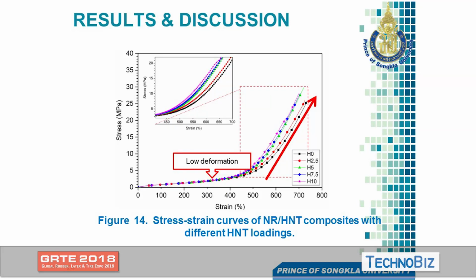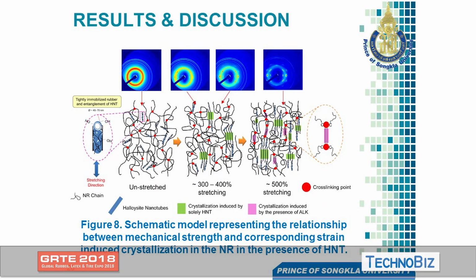Over here, it's almost the same. So that means we can make a correlation between the tensile properties and the crystallization of the natural rubber filled with HNT. Here is the schematic illustration representing the strain-induced crystallization. Once the sample was unstretched, nothing happened in the 2D image. But once we increase the strain, we can see a clear indication of the crystal image over here.